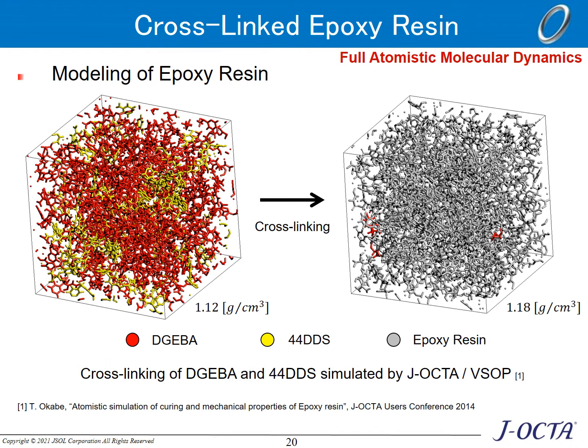This slide shows the curing reaction of epoxy resins. Using molecular dynamics, the motion of the molecules can be calculated on a scale of about 10 nanometers. VSOP is used as the calculation engine. In the left figure, the red color indicates the main agent, and the yellow color indicates the curing agent. After the calculation, the color of the molecules is almost entirely gray, as shown in the figure on the right. The same color represents one molecular species, which means that most of the molecules react and are connected to each other.